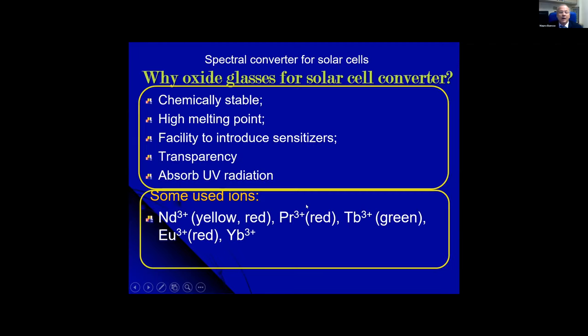In our lab, now the second area, spectral converter for solar cells. As I said before, there is a mismatch between the solar spectrum and the silicon solar cell, and we are trying to get this material with doping using the idea of one ion that absorbs with a high absorption coefficient in the visible region where the sunshine has the most intensity, and then through a downconversion process, transfers the energy to ytterbium, where the emission from ytterbium 3+ is exactly at the maximum where the silicon band gap works. So it could improve the emission and the efficiency of photovoltaic cells. This is a very recent subject, and there is a lot of research in this direction, trying to get some material.